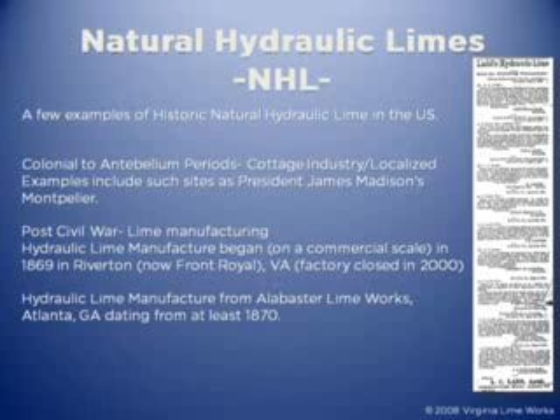But before the Civil War, the antebellum times, most all lime was a cottage industry. If a bricklayer needed mortar, he quarried his own limestone, or he got his limestone, burned it in a little kiln, or a farmer burned it in his kiln, and they made it. Now if that limestone had silica or aluminates in it, you were going to be making a hydraulic lime. And if you were using a hot lime mortar, not a lime putty mortar, you would just notice that this lime is really good. It makes a very strong material.